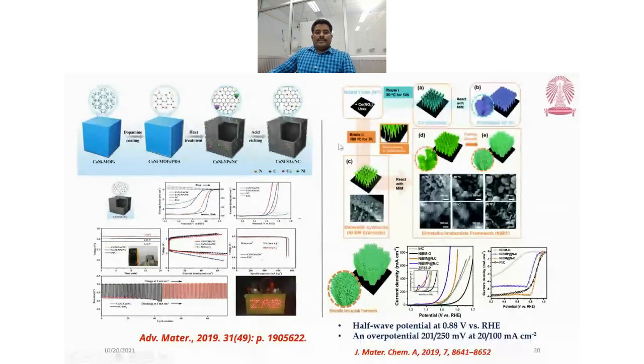This is another interesting technique they use to synthesize the MOF directly on the nickel foam. During the pyrolysis, the cage structures are formed. It is a self-supported MOF. This MOF has excellent activity towards the OER and ORR processes, and it gives a better performance for zinc-air battery.